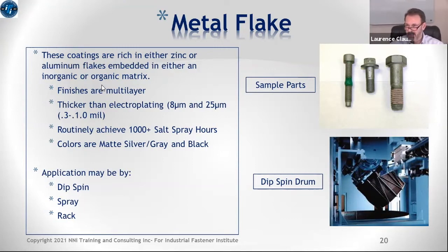They essentially take a metal, usually zinc or aluminum. They take very fine sintered powder or flakes of that metal, and they mix and embed it in a base matrix. That base matrix is very much like paint, and so essentially the part gets dipped into this paint-like material.